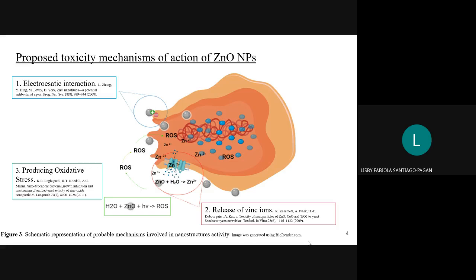These ROS are, for example, superoxide anions, hydrogen peroxide, and hydroxide, and they can participate in the destruction of cellular essential macromolecules. ROS can also oxidize proteins and lipids, which can damage the cell membrane, impact permeability, and inhibit essential metabolic processes. However, alternative studies have shown that ROS activity can occur in the dark, so further studies are needed to better understand the cause behind this potential mechanism.